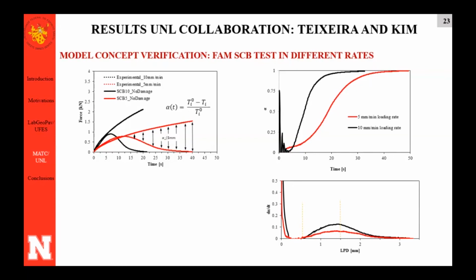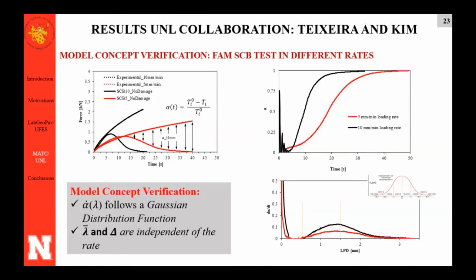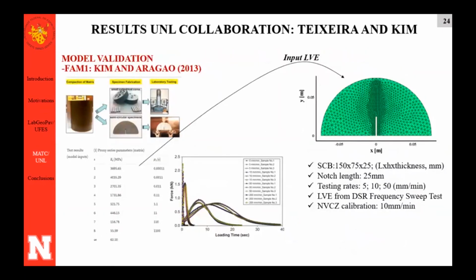The two parameters that are required for the Gaussian distribution function are the position of the mean value and the standard deviation. Even if I change the rate, the peak position is the same. So it's rate independent. And the delta value, this big delta, is the standard deviation of the values found throughout the analysis data. So conceptually, this model may work based on this analysis. So I tried to validate. So we went for validation.